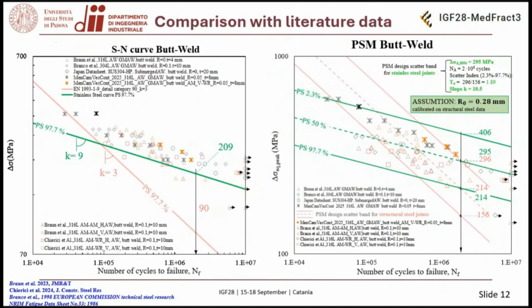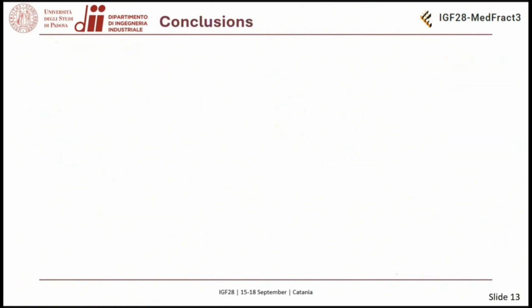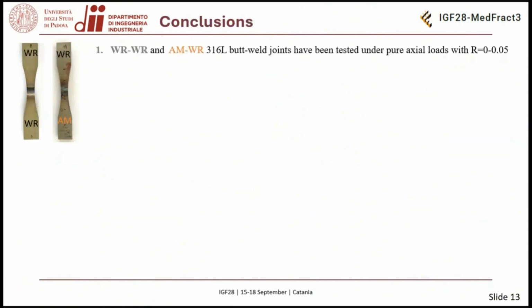And also we compare our data with this curve and this scatter band defined for austenitic stainless steel, but traditionally manufactured welded joints. And as you can see, also in this case, they are in good agreement with this new curve and scatter band. And so to conclude, we tested butt welded joints, both traditionally manufactured ones and joints with an AM part, in a pure axial loading condition with the loading ratio almost equal to 0.